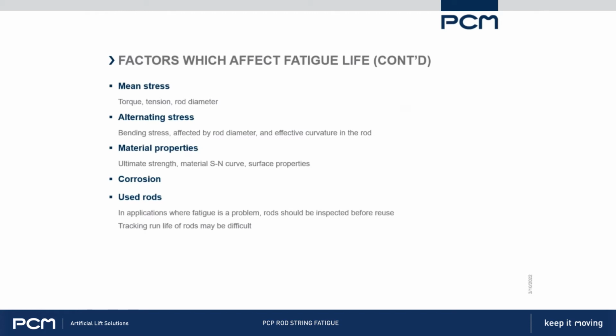That leaves a certain surface finish, which will have its own likelihood of causing fatigue problems or its own effect on the fatigue. If you were to polish your rods, of course, you'd remove a lot of the surface imperfections and you'd get better fatigue life, but nobody's going to run a whole string of polished rod. That would just be too expensive. But what is a surface property that is relevant here is that most sucker rods, the manufacturers use a process called shot peening. After they manufacture the rods, they go through this process which puts in some residual stress in the surface, and that is supposed to improve fatigue life as well.